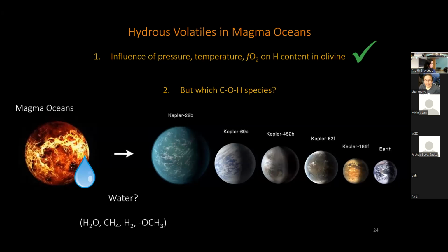Okay, so I've answered the influence of pressure, we've looked at temperature, and I've shown that the oxidized and the reduced samples follow two distinct trend lines. We also see that the initial water content of the sample really determines how you interpret those trends as well. The next part I want to talk about is which COH volatiles, since I've only really talked about bulk hydrogen contents that I've analyzed via SIMS. Now I'm going to see if we can decipher which COH species we have in the melt. And perhaps this will explain why the reduced samples are different than the oxidized.